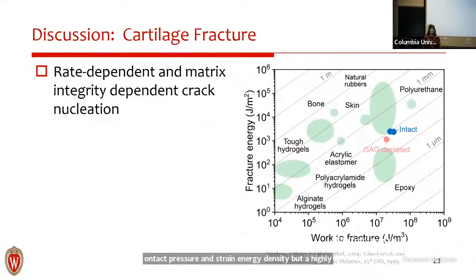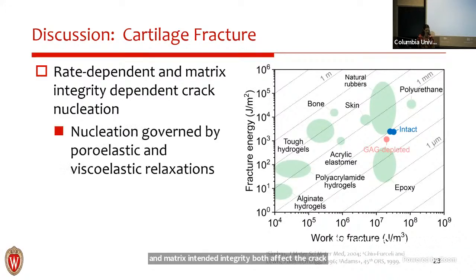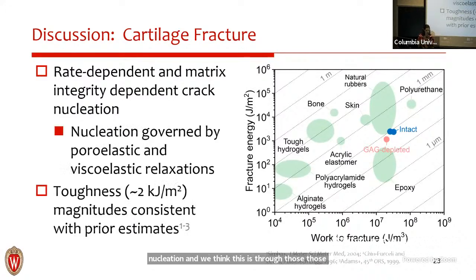All right, so I'll wrap up this first part of the study and then we'll jump into some metabolism work. So for the cartilage fracture, some of the key things that we've shown so far is that rate and matrix integrity both affect the crack nucleation. And we think this is through those poroelastic and viscoelastic relaxations. And then our toughness estimates, we do see they're similar magnitudes that are consistent with prior estimates. So we think that the method we're using to estimate this fracture toughness is reasonably reliable.